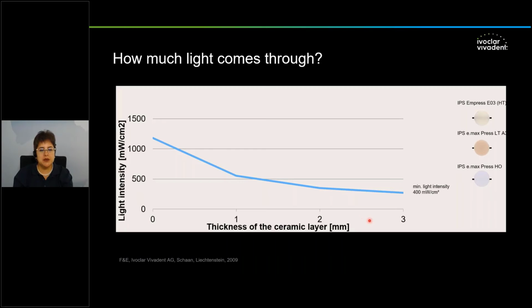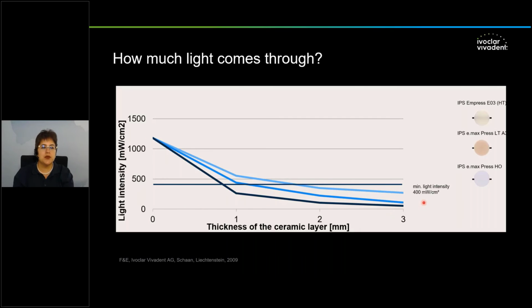With the materials, you see that they use different thicknesses, 1, 2, and 3 millimeters of ceramic, and they just put it in between for the measurement. You also see that the thicker the ceramic, the less light passes through it. And you see it also here with the high opacity, it is really unbelievable. We start here at 1,200, and we know that a minimum of 400 milliwatts per centimeter square is necessary so the resin parts are able to polymerize by the light curing.